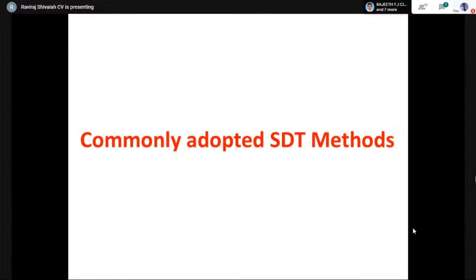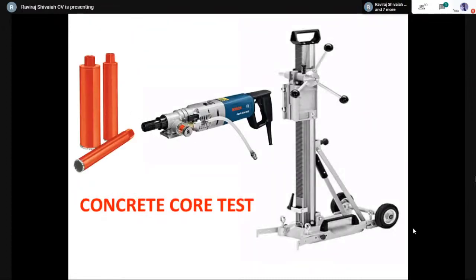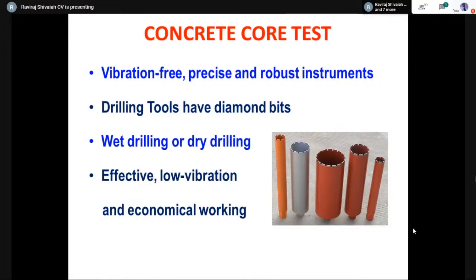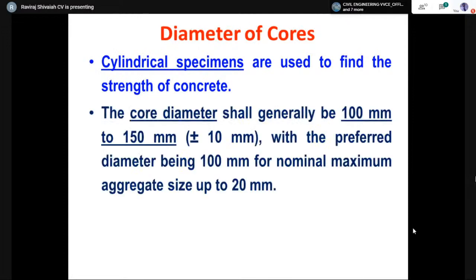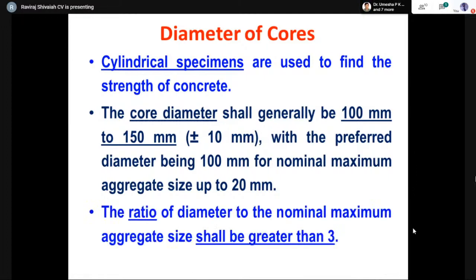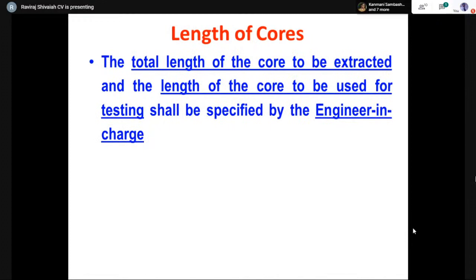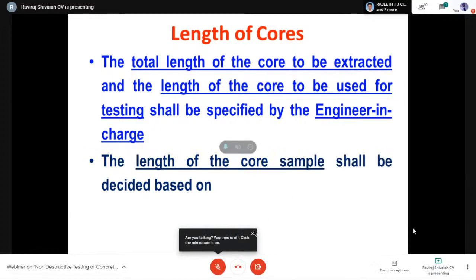We can know the kind of defects in the concrete, correct? Now let me take you through the core cutter. Please understand, this is a very standard test that we normally do in case of a core cutter, where we use different kinds of tools to take cores. The cores are normally cylindrical specimens. The diameter varies from 100 to 150 mm. The standard size generally used in the field is 100 mm. And we can also see that the diameter is at least three times more than the nominal maximum size of the aggregate. And the total length of the core that we normally extract will depend on the engineer-in-charge that we are trying to have here.